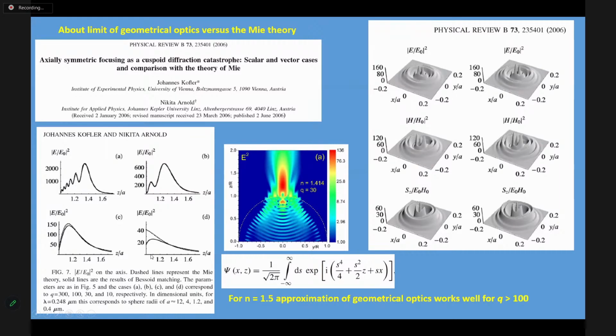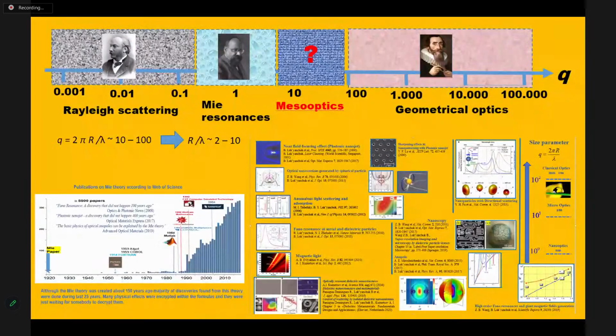For example, here for refractive index, I forgot to say 1.5 for glass. You can see that with size parameter equal to 10, we can see a difference between Mie theory and the approximation of geometrical optics. The same, we can see a difference at size parameter 30, and finally, when the size parameter becomes 100 or even higher, then we obtain good agreement between Mie theory and geometrical optics.